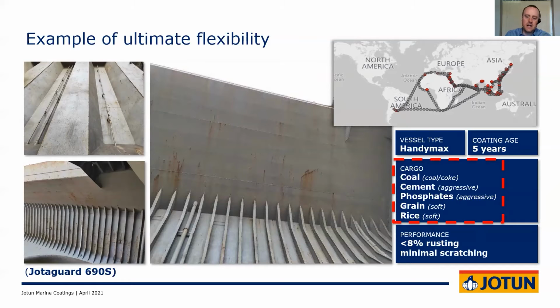Finally then, looking at a top of the range pure epoxy type product, something with very high tensile strength and scratch resistance. You can see it's exhibiting no corrosion creep from the small areas where there are minor damages, and the results have been less than 8% in total rusting. After what's been an extremely demanding cargo trade, you can see the cargoes listed here, and there are very hard, very high impact cargoes, but there's also the high sensitivity cargoes, the foodstuffs and such.